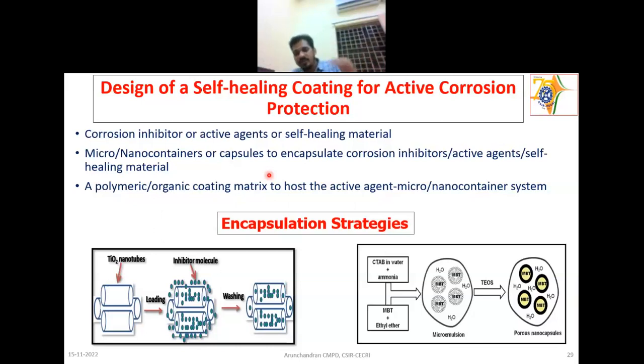So there are things, then later people found out they made the polymeric shell wall using a hybrid material, silica plus polyurethane kind of thing. Those things are also available now, but most of them are in the academic journals and papers only, nothing in the market as of now. And then you need to have a proper polymeric organic coating matrix of the active agent.